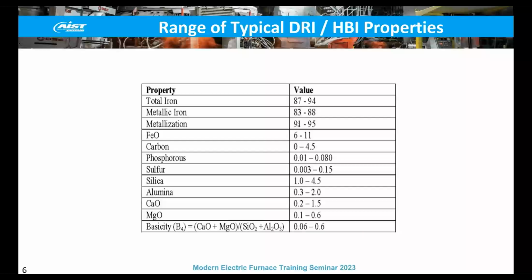As it sits around longer, depending on the environment it's stored in, it can begin to react a little bit. So you always end up with some FeO, depending on how and where it's produced, carbon between 0 and 4.5%, some amount of phosphorus generally. If it's coal-based, you'll have higher phosphorus and probably higher sulfur, whereas if it's more gas-based, you'll end up with lower phosphorus, lower sulfur content. You'll also end up with some silica, alumina, so it has a relatively low basicity.